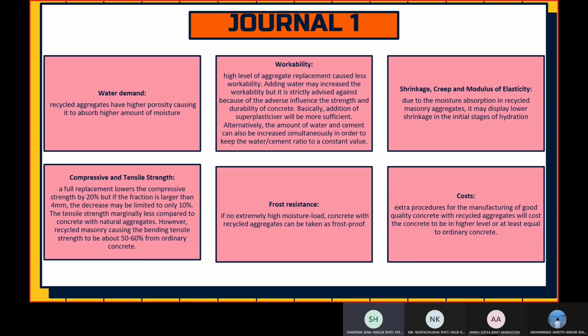Next, frost resistance. If there is no extremely high moisture load, concrete with recycled aggregates can be taken as frost-proof. In case of high moisture load, the application of recycled masonry should be avoided for outdoor application. The ability for water and chloride to penetrate deeper in concrete with such aggregates can cause frost damage. And the last property discussed is the cost. Extra procedures for the manufacturing of good quality concrete with recycled aggregates will cause the cost to be at a high level or at least equal to ordinary concrete.